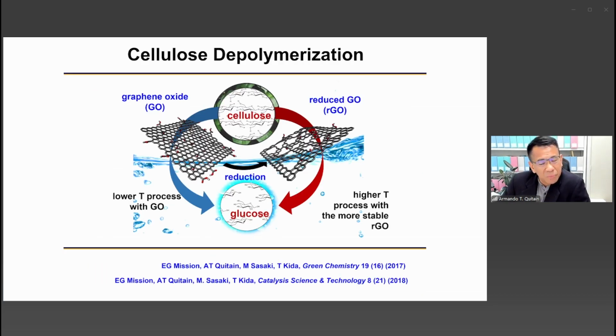And well, we can also use, instead of graphene oxide, a more stable reduced graphene oxide. But this will require a relatively higher temperature of 220 degrees centigrade. So reduced graphene oxide performs similar to that of fresh graphene oxide in order to get glucose, but as I have mentioned, at a relatively higher temperature. The good thing is reduced graphene oxide is more stable than that of graphene oxide.